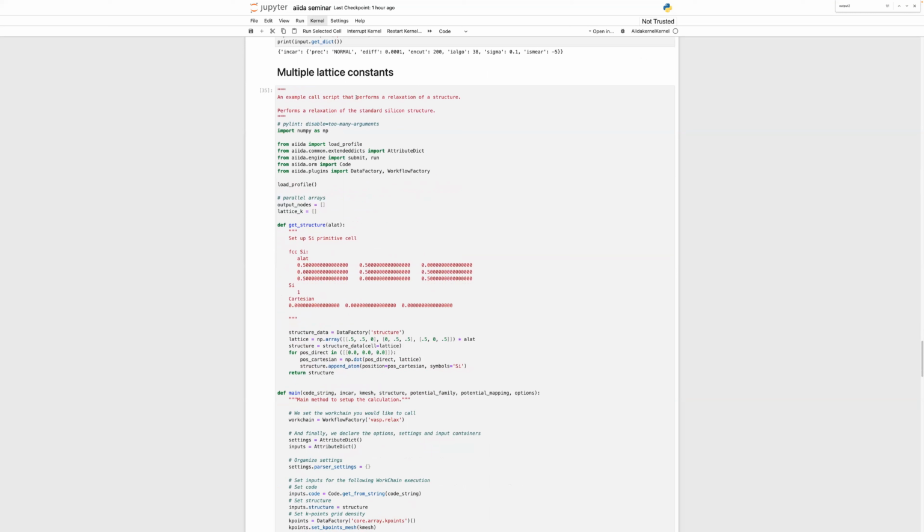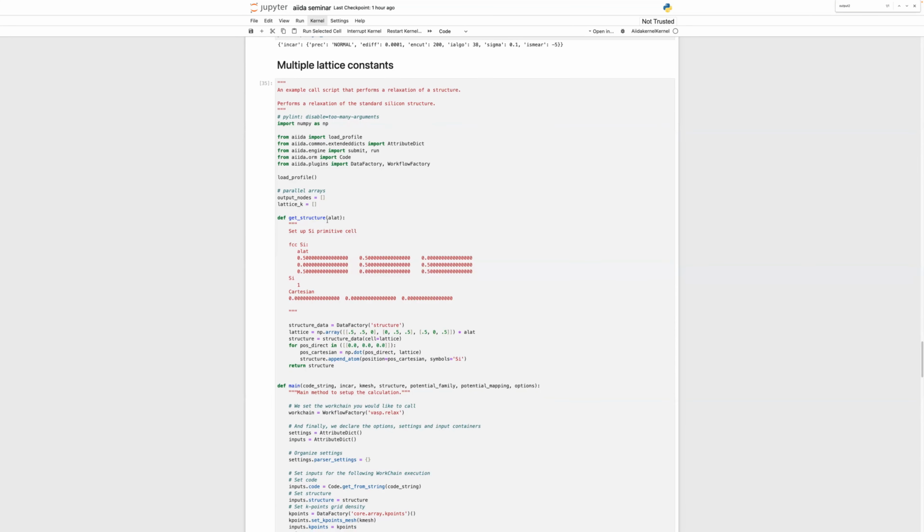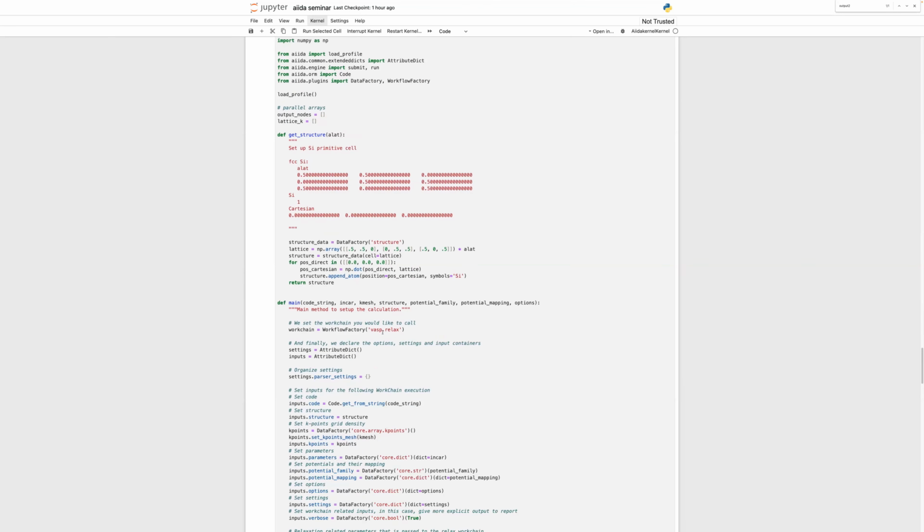So this is actually a little bit of a different problem than what we have seen before. Now this is a true FCC structure because there are 4 atoms in the unit cell. What I want to do here is try different unit cell volumes and compute the energy for particular volumes of the unit cell to find the minimum, and the minimum will correspond to the true volume of that crystal. So now I have a get structure function which takes a parameter, and this parameter is just a scaling function, which shifts the atoms depending on how I change the volume of the unit cell.